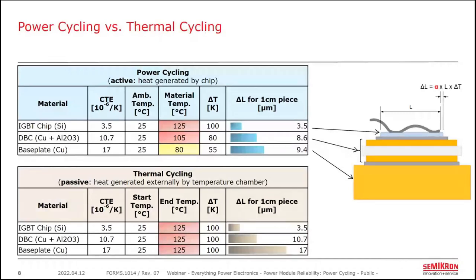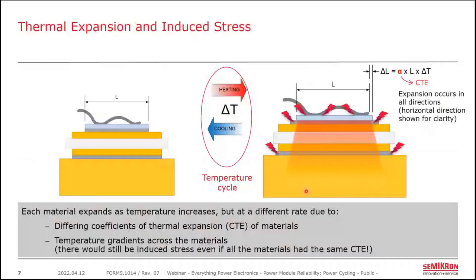So yes. In higher performance modules for the traction environment, again, railway, trams and trains and such, the copper base plate is replaced by an AlSiC base plate, aluminum silicon carbide, that has a lower coefficient of thermal expansion. So yes, that is absolutely an option. The two issues, one is, of course, cost of the material. Two is that, as I mentioned here, even if you do match those CTEs perfectly, say you match the base plate to the solder and you match the solder to the copper, et cetera,